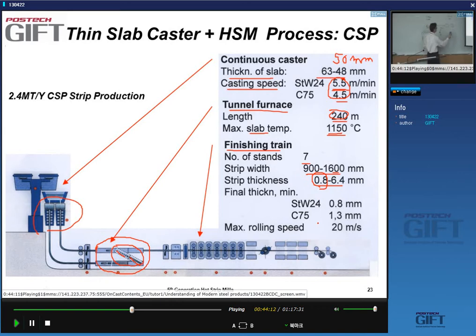conventional hot strip mill will rarely have thicknesses less than 3. Yes, it's not impossible. Okay, there are hot strip mills that can produce 2.5 millimeters, but in general most produce 5 to 6 and thicker material. Yes, in the case of a compact strip mill or ISP technology, you can easily go to the millimeter domain of casting. So millimeter thicknesses are not a difficulty. And typical finest thicknesses here, you can see here for some low carbon grades are around a millimeter.